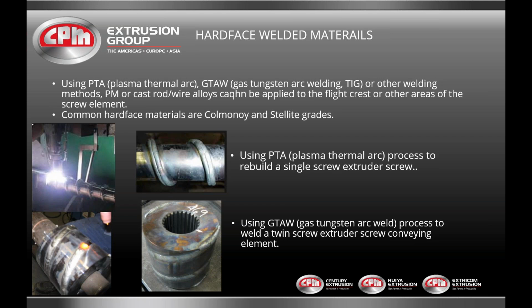The top two photos are showing the plasma thermal arc on a single extruder screw, and the bottom photos are representative of a TIG welded screw element. We typically groove those prior to forming the screw element or machining the screw element out of it—that's why it just looks like a cylinder with some weld around it. But they're grooved, and we fill the groove with the hard face material.